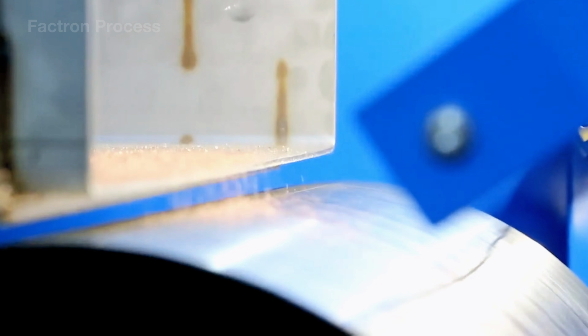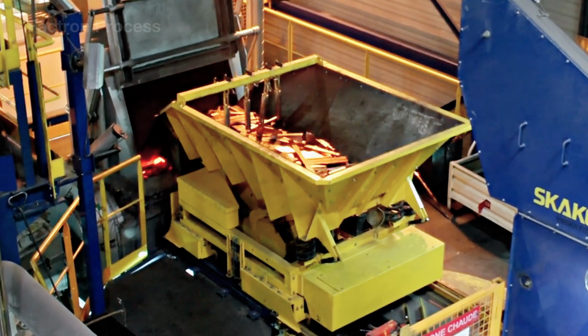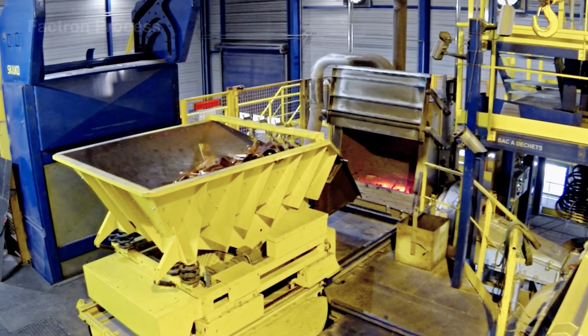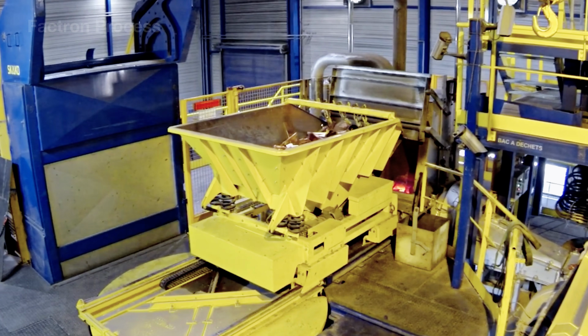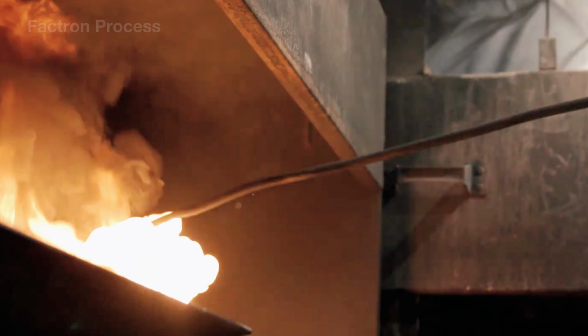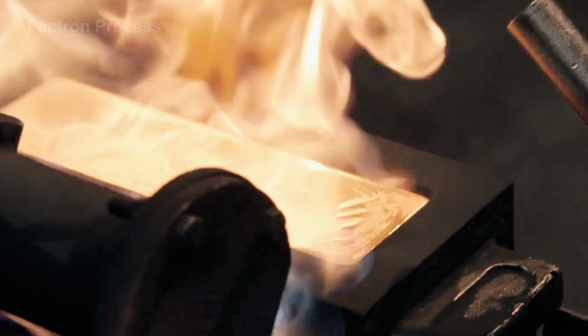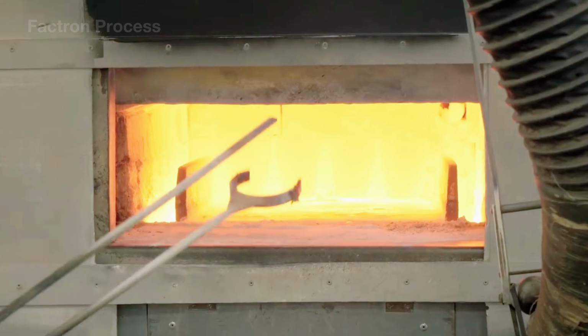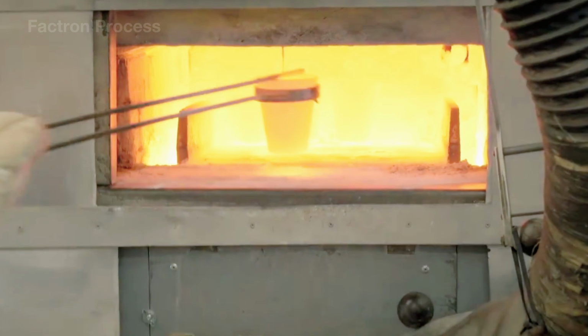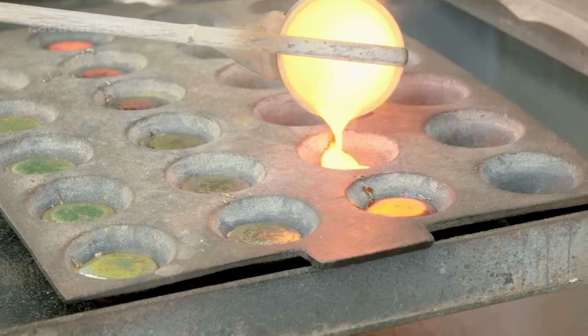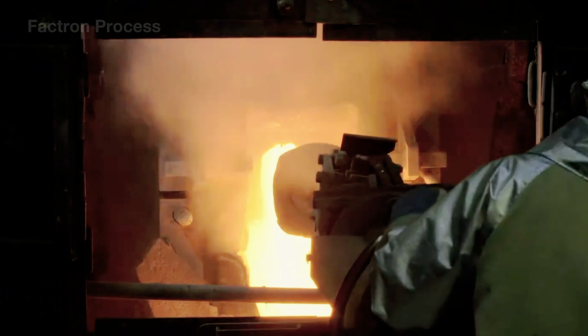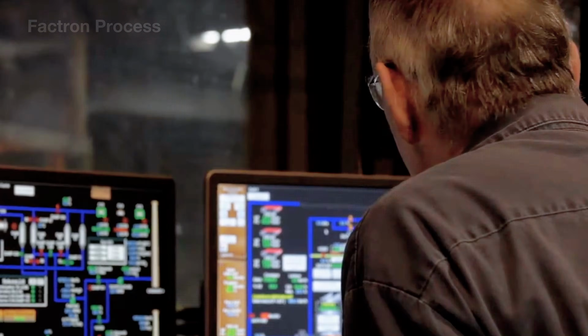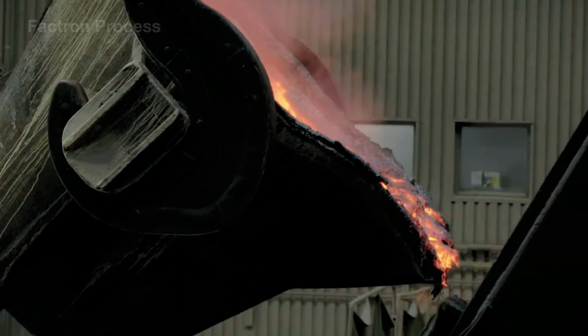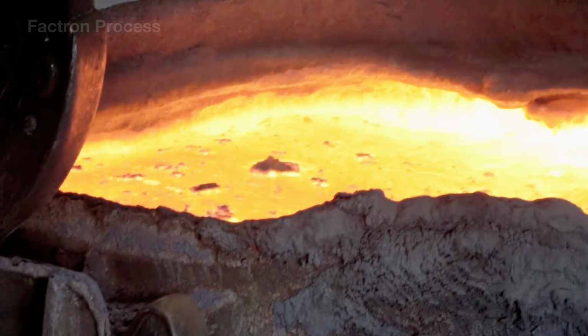Magnets separate iron, while XRF scanners identify metal composition within 2 to 5 seconds. A modern line can process between 20 and 50 tons of scrap per hour. Electrical wires and cables pass through stripping machines before the copper cores are cut and reduced to particles measuring approximately 3 to 8 millimeters. Screens, airflow systems, and gravity tables then remove plastic, iron, and lighter materials, producing copper granules with a purity of 99% or higher.